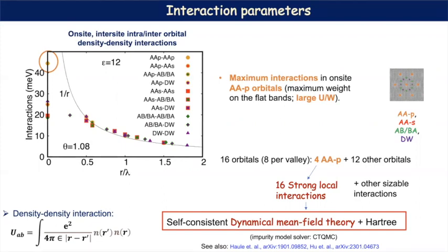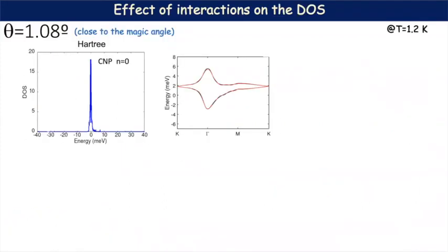So with that, I'm going to get into the results. Just to start, let me show you the general effect that the interaction has on the density of state. On the left, I'm showing you the density of state of the non-interacting system, which has these two strong Van Hove peaks, with a bandwidth of about 2 to 3 meV at this angle.